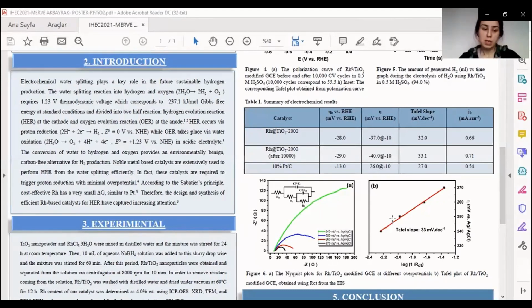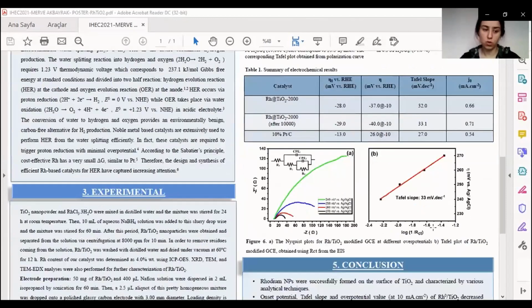Also, the Tafel slopes can be calculated by using the impedance spectroscopy results. This calculation method is only related to the charge transfer kinetics and allows us to exclude contributions coming from the catalyst resistance. And the overpotential versus logarithm of 1 over charge transfer resistance plot shows that the Tafel slope value was calculated as 33 millivolt per decade, which is quite similar to the one derived from the linear sweep voltammetric curve.